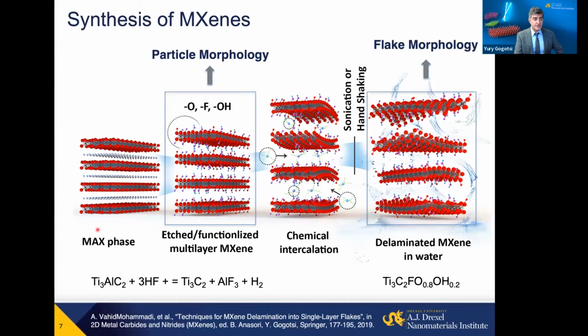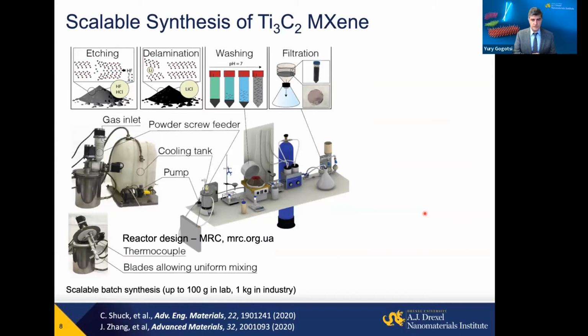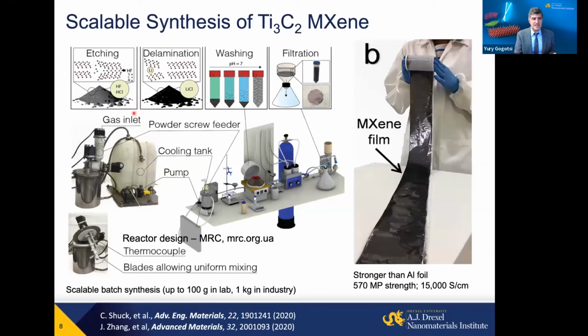So we start with the ceramic materials like MAX phase, etched, for example, in acidic etchants here, and we produce a number of materials, including single flake materials here. What is also important? It's a scalable process. We can make hundreds of grams of materials in our laboratory, kilogram reactors are in industry, but potentially we take ceramic, we put it in a container, we etch it. So it means that the process is scalable to almost probably infinite volumes here.